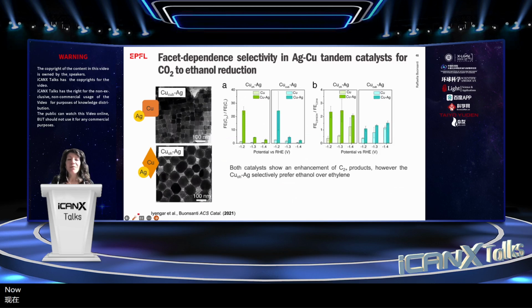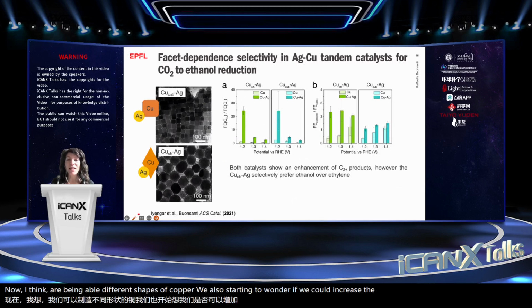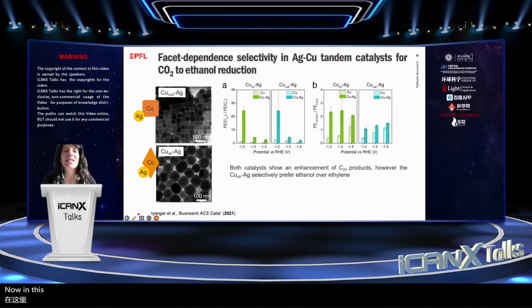Now, having available different shapes of copper, we also started to wonder if we could increase further the selectivity for C2 by maybe coupling the silver spheres with the copper cubes. And what about the copper octahedra? Now, in this case, what we found was an interesting behavior, because both catalysts were able to increase the Faradaic efficiency for C2.